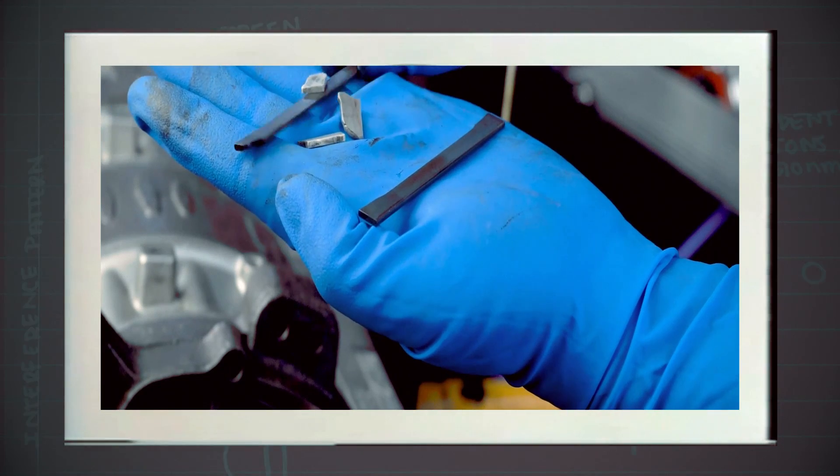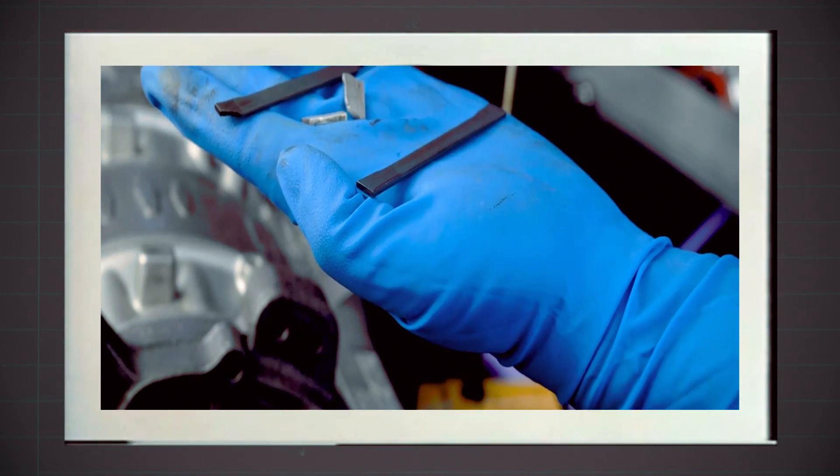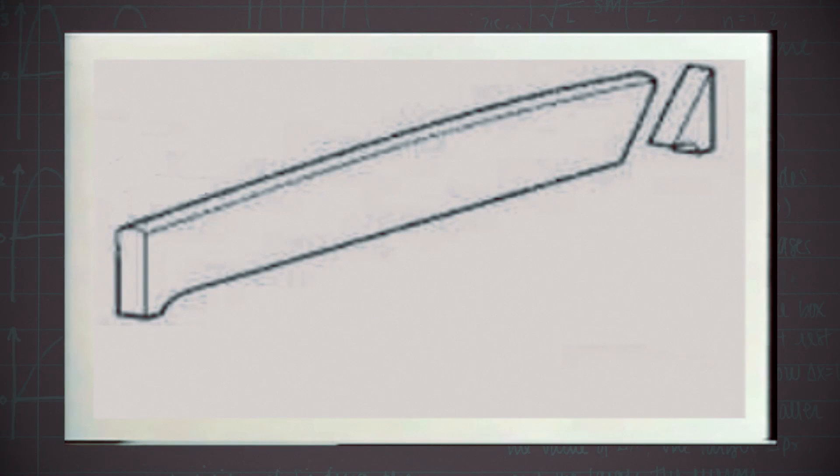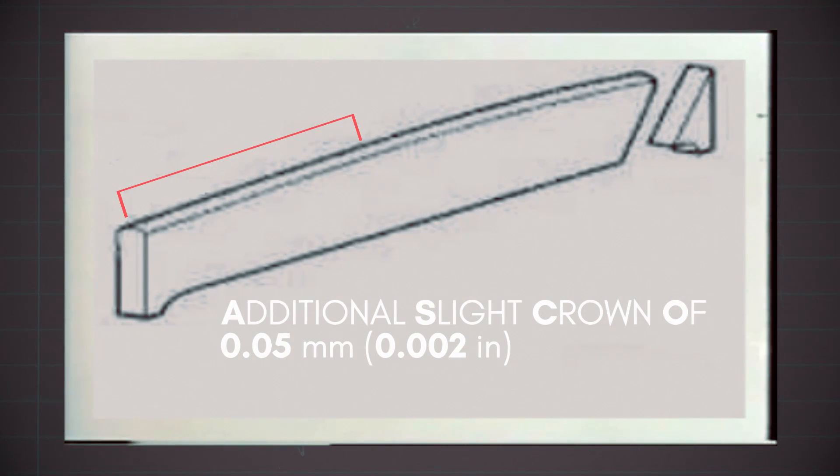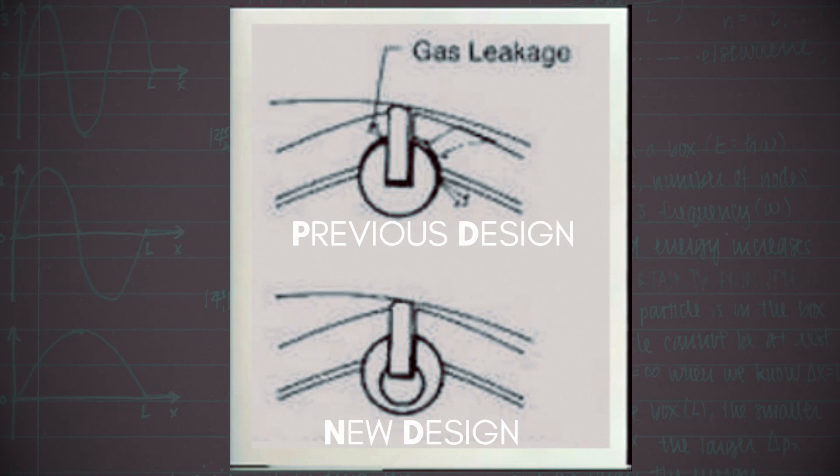From 1975 to 1980, it was discovered that the current apex seal design was subjected to high thermal and centrifugal loads during high engine RPM ranges. To rectify this issue, Mazda implemented a slight crown of .05 mm or .002 inches at the highest center section of the seal. This additional crowning compensated for the rotor housing slight deformation under high loads, ensuring sufficient contact with the rotor housing walls under operation. Mazda also improved the corner pieces by incorporating a spring design to keep the clearance of the rotor groove at a minimum, dramatically improving gas sealing over the solid springs used on the previous version.